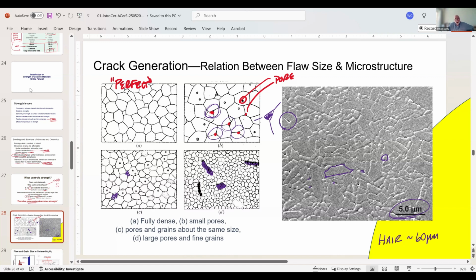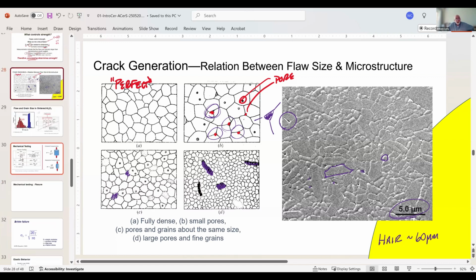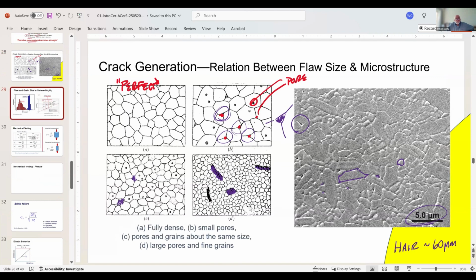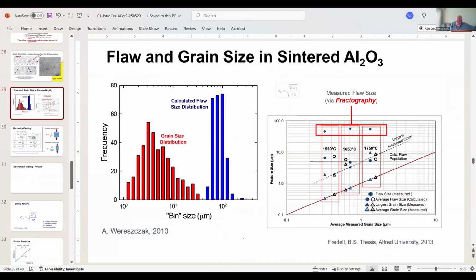But a friend of mine at Oak Ridge, Andy Wereszczak, sent me this data many years ago. And this is a size indication here. It's a bin size, so he grouped things by size on a log scale. So this is 1.0, this is 10, this is 100, here at this mark. So he measured the grain size distribution in about 400 to 500 grains. And then he calculated the flaw size distribution based on the strength data.